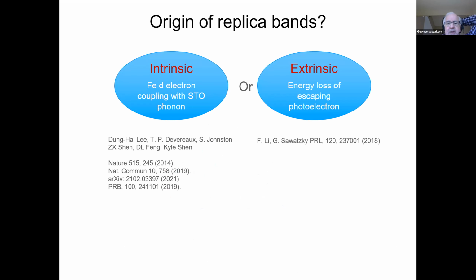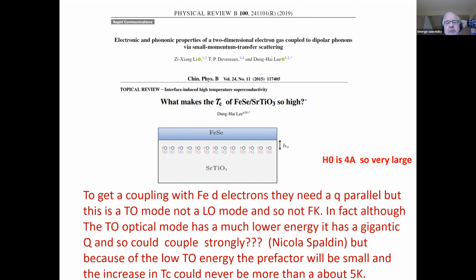Okay, so is it extrinsic or intrinsic? So many people have tried. There's been theory done, a very beautiful work done by Lee, and on this. And a recent paper, for example, they had also with Tom Devereaux, they had this picture of having oscillating dipoles like this, and they did a quantum Monte Carlo type calculation, oscillating dipoles polarized in the Z direction here, in the vertical direction, and they calculated what a d electron in iron selenide, by modeling it with a tight binding like model, how it would couple as it moves through the iron selenide.